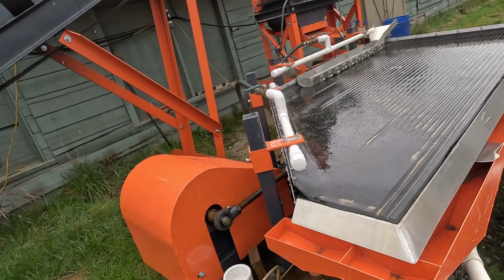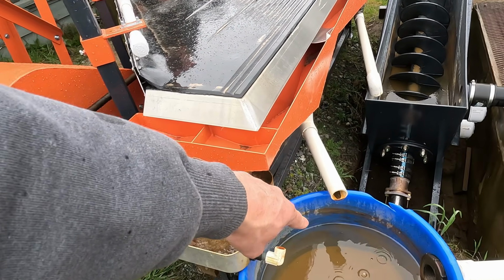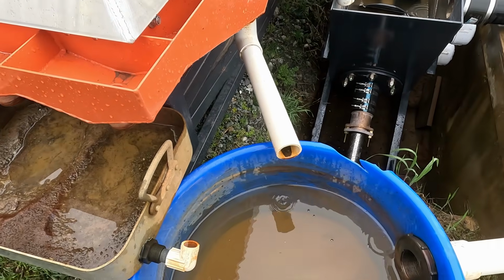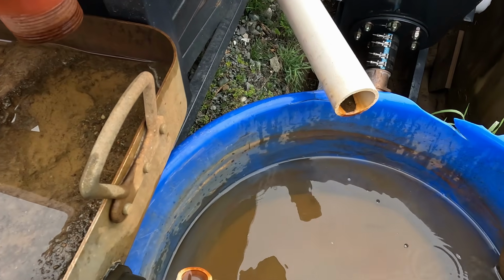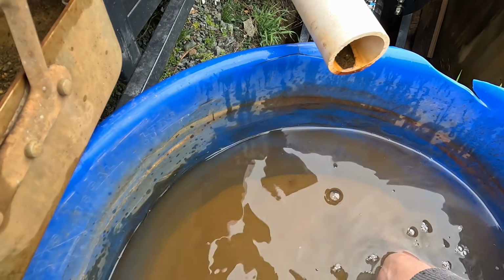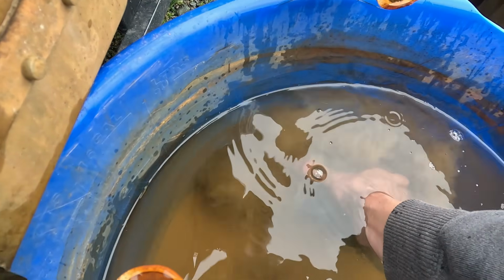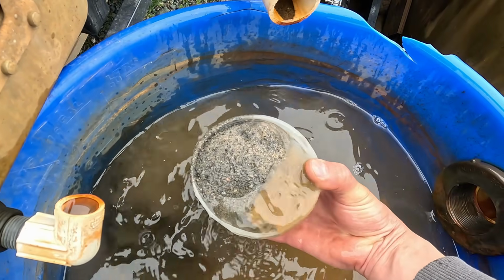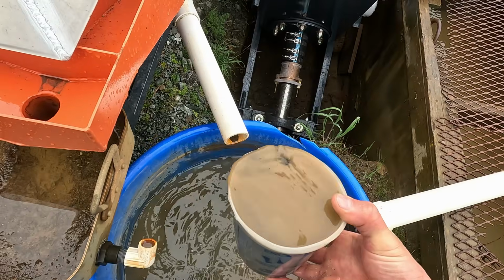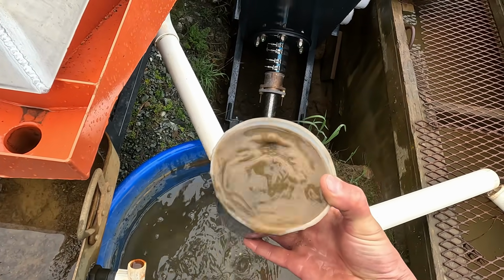So now what we're gonna do is we're gonna go out to the shaker table here where we ran our samples, and we're gonna get some of the number 3. What we're smelting now is the number 2 panning tailings. I panned out all the gold out of the number 1 and number 2, and that's what's left over. This stuff here is the number 3 that comes off the shaker table right here. And this will be a significant amount of sulfides. There should not be hardly any free gold in here. But we're gonna try a batch of this next to see if there's any gold in here.